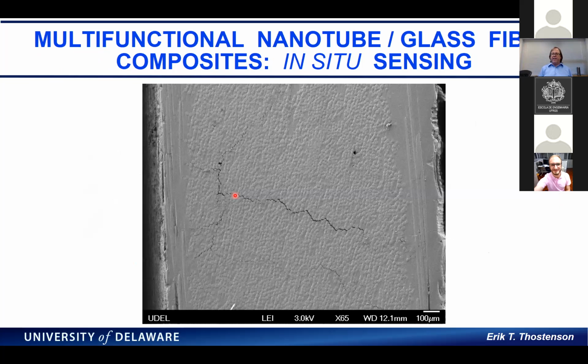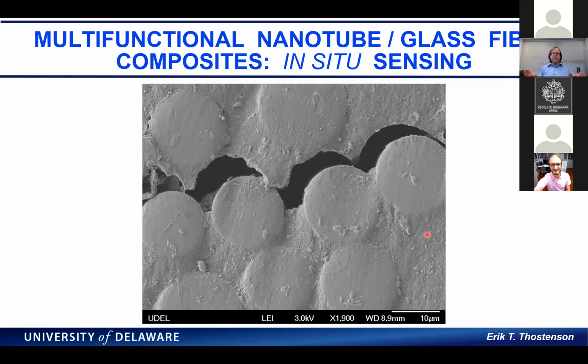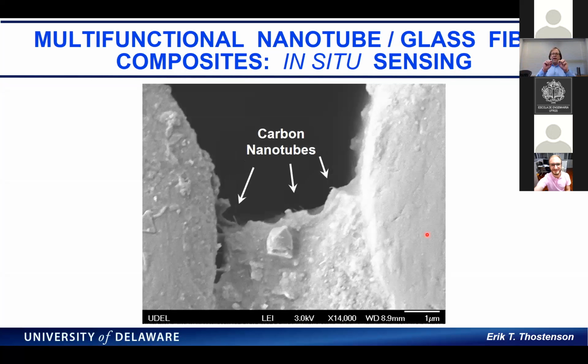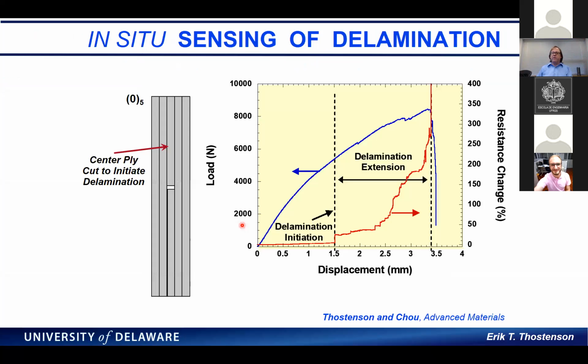This is where I have a crack in a cross-ply laminate. The circles that you see here are the fibers that are going into the plane of the screen, and you can see the crack going across that layer. If we zoom in a little bit, you can see the individual fibers, and you can see it's debonded at the interface and cracked between the individual fibers. And now if we look in between the two fibers, we can see right at that edge the nanoparticles, in this case the nanotubes, sticking out. So we're creating those conducting pathways, and the cracks are breaking them. So this was pretty exciting that we could see this, but could we use this to detect damage?